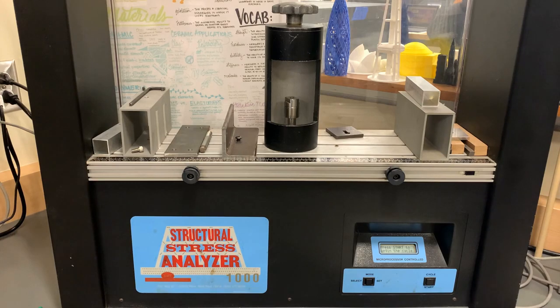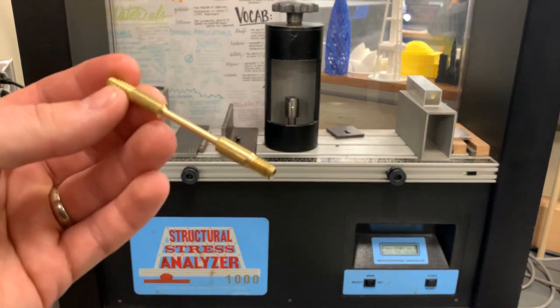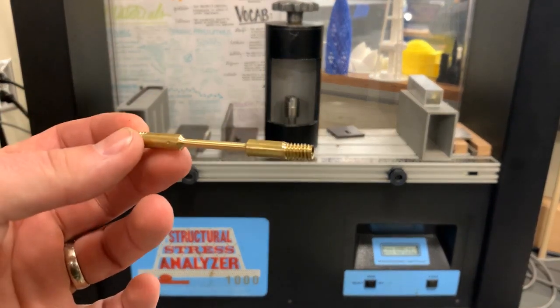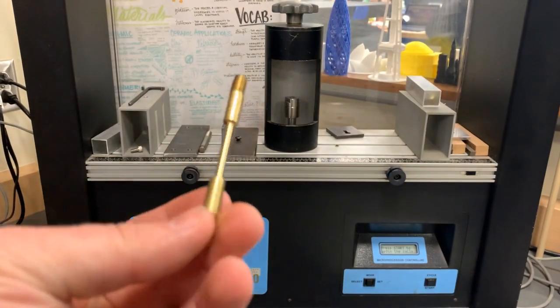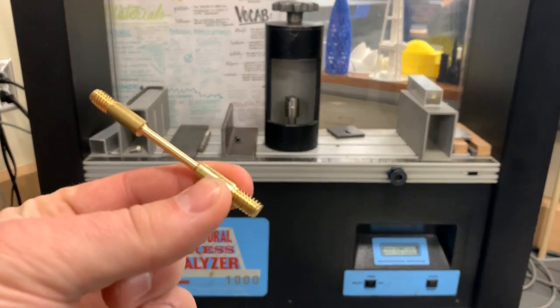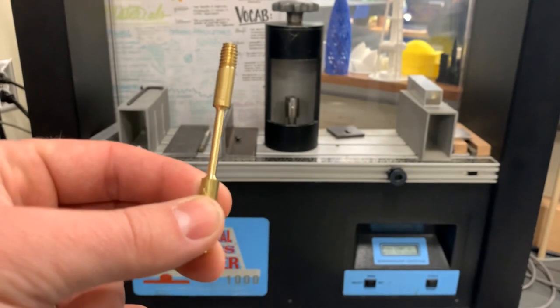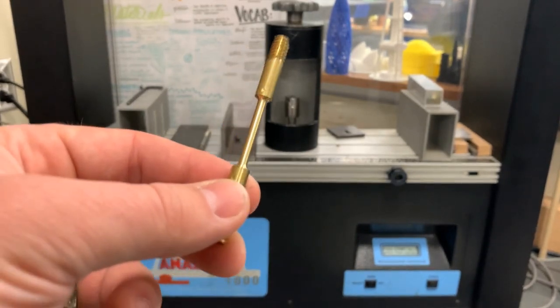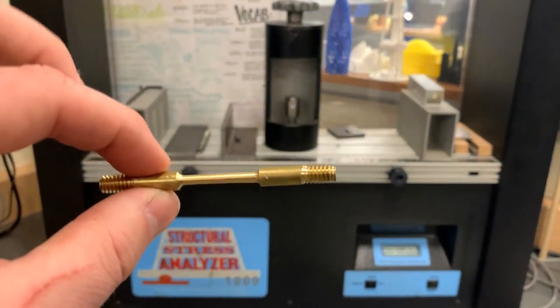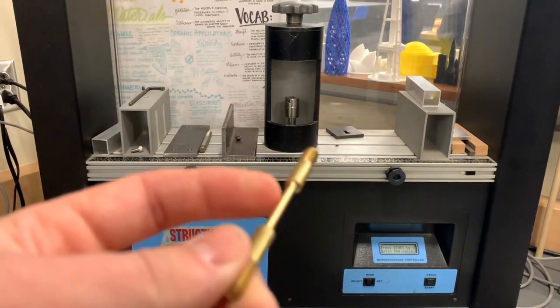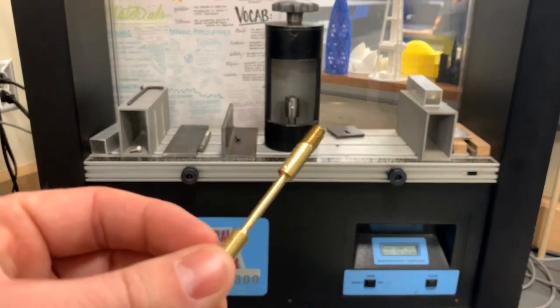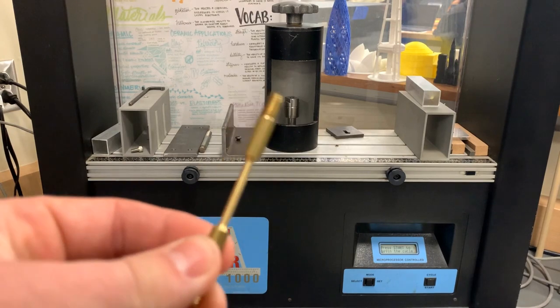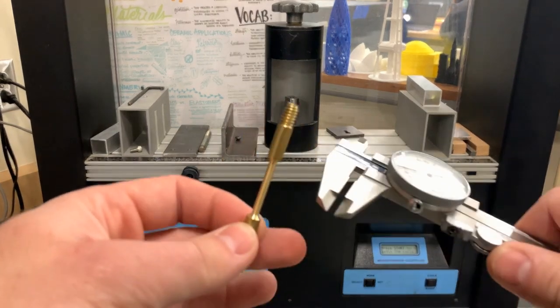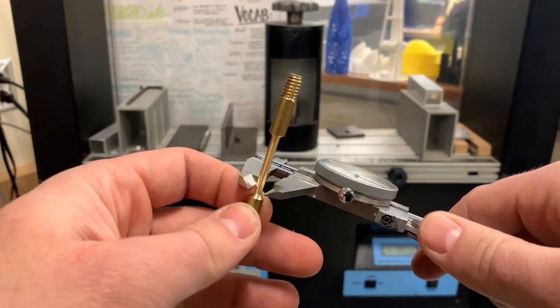All right, this video is going to show you how to perform the tensile test on your dog bone sample that you made in the machine shop. Before we do anything, you've got to make sure you get your measurements from your sample so that you can correctly do the stress strain calculations that come a little bit later. So the target diameter for this was 0.125 inches, but don't just do your math with that number. Actually use a pair of dial calipers and check your measurement.